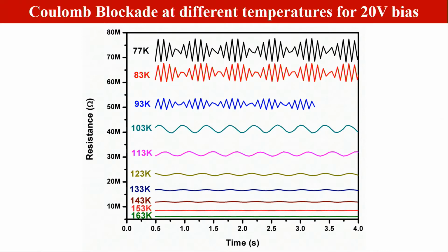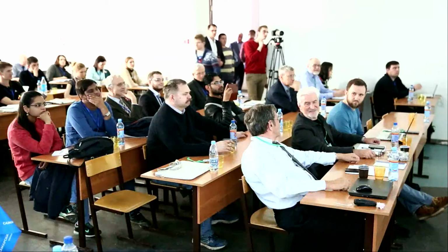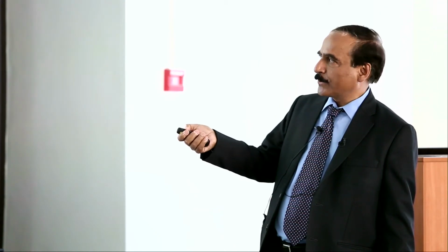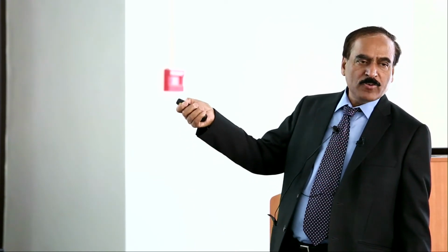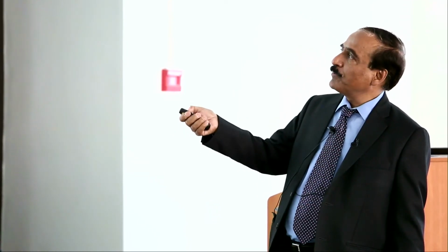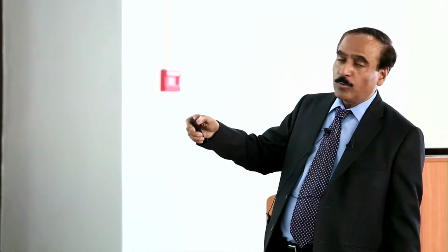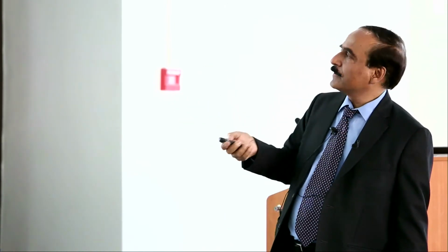Okay. And the moment we are decreasing and decreasing, one important point is there. These are the Coulomb oscillations, because when the current is passing, you get a peak, and when the current simply goes away, then there is a slump, because it is behaving like a blockade situation, and again current is passing when the electron is passing through the device. The interesting point is here, at 93 Kelvin we see some envelope oscillations. This envelope oscillations, basically the amplitude of oscillations, keeps on increasing if you go more and more to the lower temperatures.